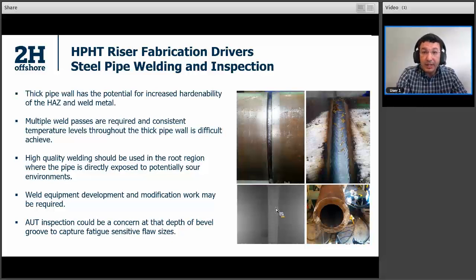One other thing is that consistent temperature levels throughout the pipe wall thickness are difficult to achieve. In conventional welding technology, the pipe is preheated before welding using conventional torch flame technology. Basically, you use a torch to heat your pipe from the OD, and you have to maintain a consistent temperature from OD to ID. Making the temperature levels consistent from OD to ID may be easier for thinner wall pipes. But if we are talking about 1.9 inch or 2 inch wall thickness pipe, maintaining consistent temperature levels from OD to ID is difficult to achieve. The fabricator needs to make sure that preheat levels at OD and ID are around the same temperature. So that's another challenge making the fabrication more difficult.